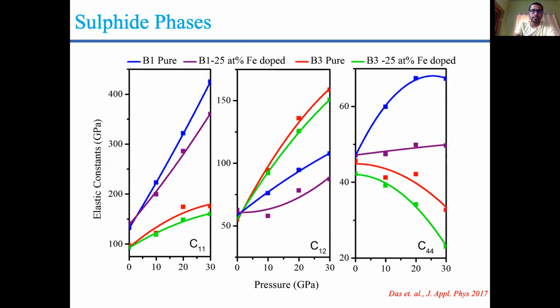So you can see, as the pressure increases, the elastic constant increases almost linearly for C11, which is the principal directional constant, and C12. But the mysterious thing is the C44. You can see for the B3 phase, for pure as well as the Fe doped phase, it decreases.